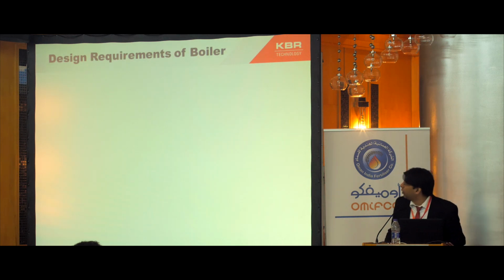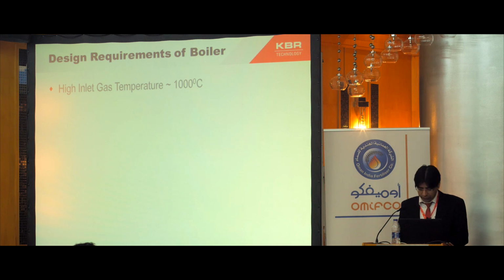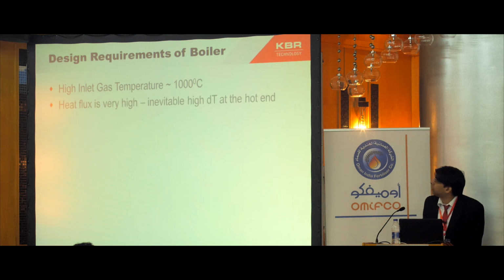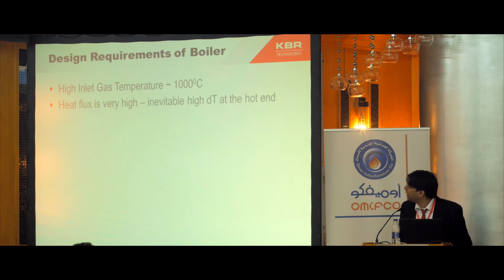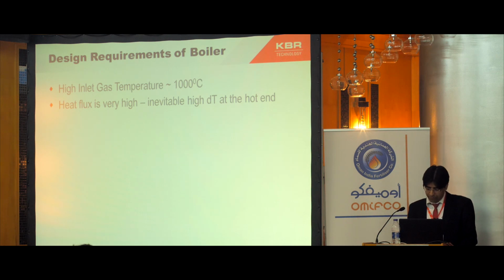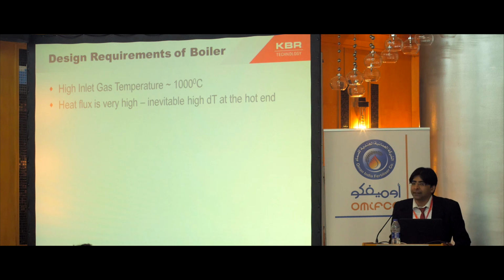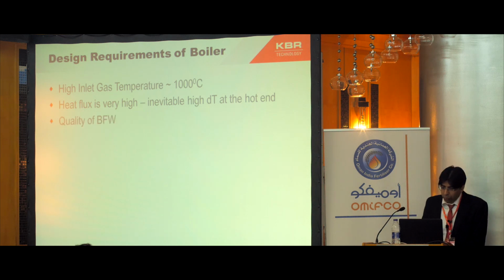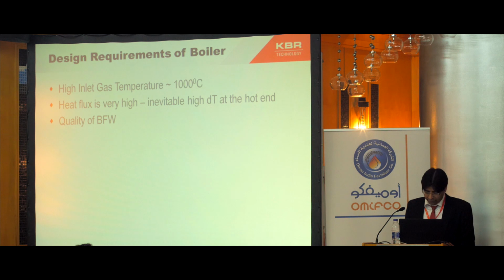Reviewing the design requirements of this boiler, we see that the gas temperature entering the boiler is 1000 degrees C, which is extremely high, and it also leads to very high heat flux with an inevitable high DT at the hot end. ASME guidelines state that this heat flux will require above normal boiler feed water treatment practices. This service is very sensitive to boiler feed water chemistry. So if it becomes abnormal, it will lead to corrosive failures of this